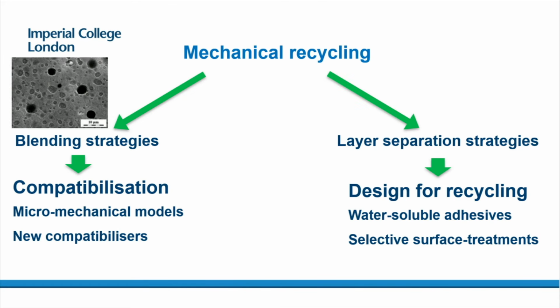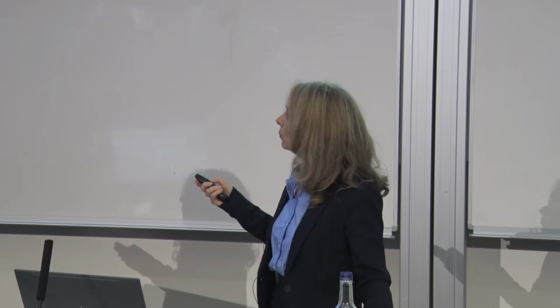The second thing that we're doing is we're trying to look at layer separation strategies. So what if you didn't use those very strong adhesives? You could then separate the different individual films in the multi-layer package. Or what if you didn't have perfect bonding throughout? You don't really need that. So then when you shred it, you can separate the films very easily and recycle it in a much easier way. I'm going to tell you a little bit more about this.